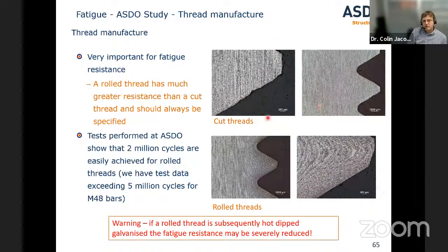So the two threads we have here, cut threads, you can see the grain of the material here. This is the rolling grain of the steel bar. So here you can see the grain's been interrupted by the cut. Here on a rolled thread, you can see the grain's been moved. This has many advantages and gives it a much increased fatigue resistance. You get a nice grain flow and increased strength around the root of the thread, which is where often fatigue will fail.